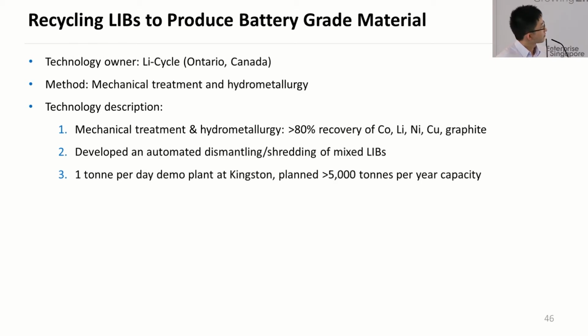Next, I'll talk about Li-Cycle. So Li-Cycle is a Canadian startup. They focus on mechanical treatment as well as hydrometallurgy, and they achieve more than 80% recovery of these raw materials. So one key thing about their process, what is so unique, is that they have developed an automated dismantling and shredding of mixed lithium-ion batteries. In particular, they focus more on the automotive type. So they have built a 1 ton per day demo plant at Kingston, and they planned up to 5,000 tons per year capacity processing the spent lithium-ion batteries.